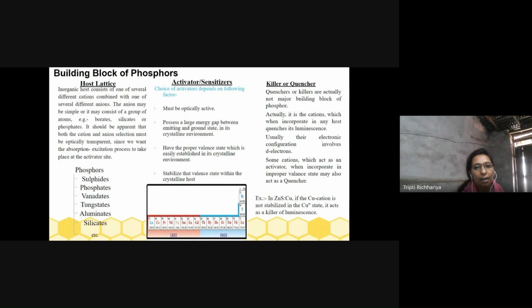Another important factor while choosing the activator is that there is a proper matching between the valence state and the size of the dopant ion and the substituted cation of the host lattice, so that the dopant gets easily stabilized within the crystalline host. There are two possibilities for the choice of activators or co-activators. The first one is the transition metal, and the second one is the rare earth element. But instead of transition metals, rare earth elements are mostly preferred, because the transition metal consists of d electrons, and we know that the d orbitals possess very closely spaced energy levels, so there is a high chance of non-radiative transition as compared to the radiative transition, and the luminescence properties get diminished.